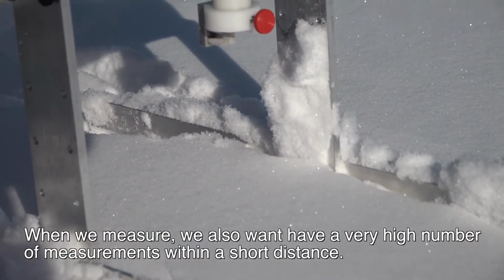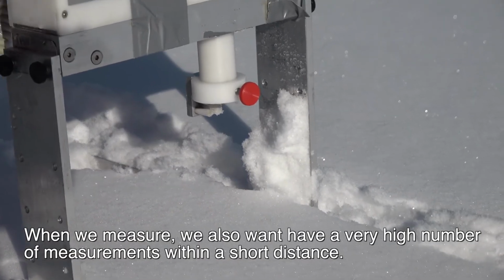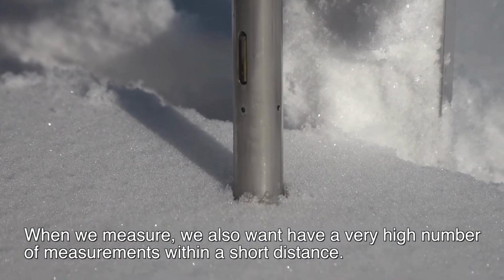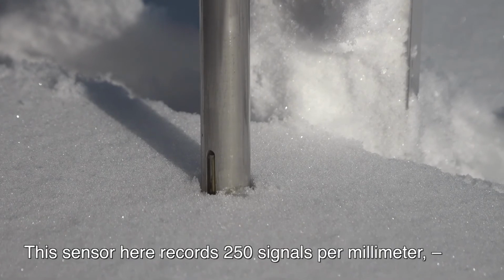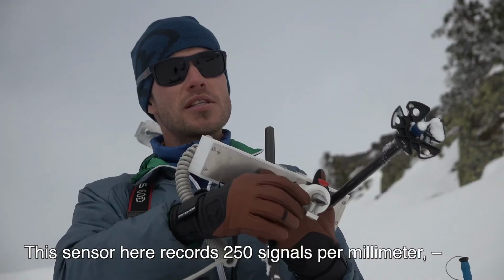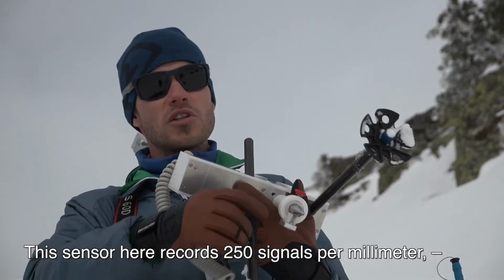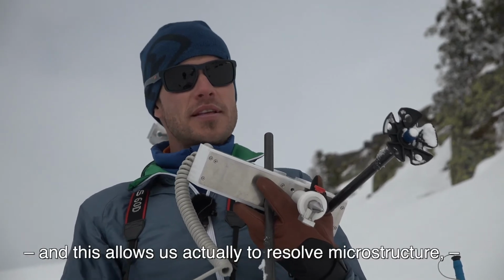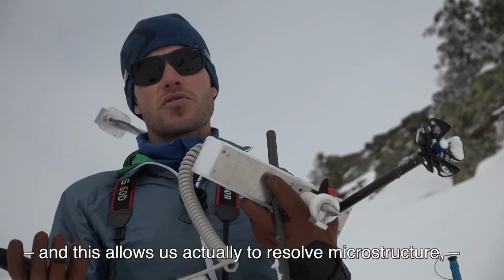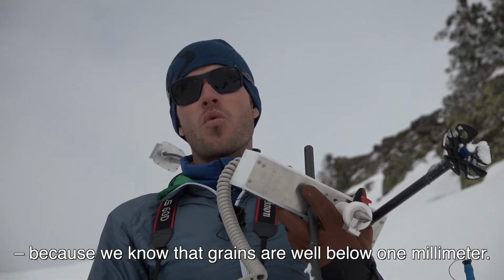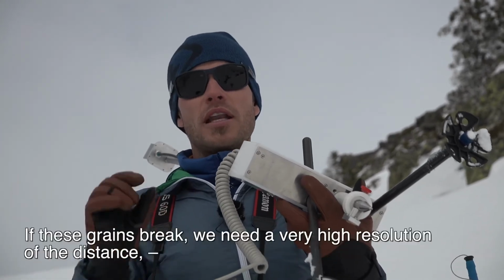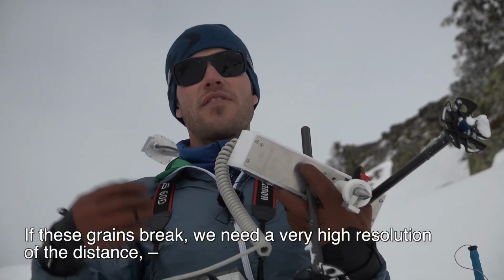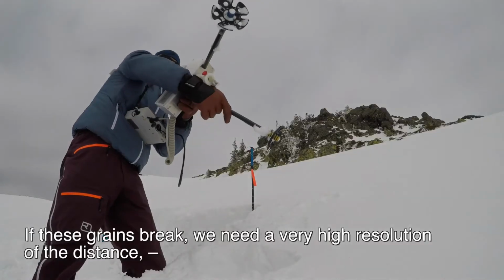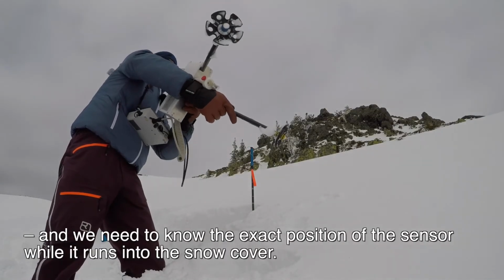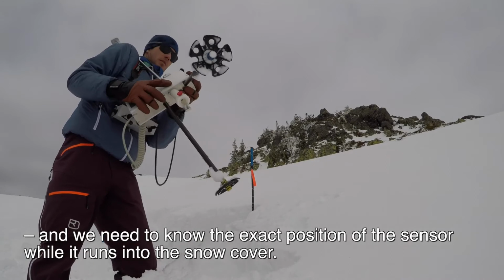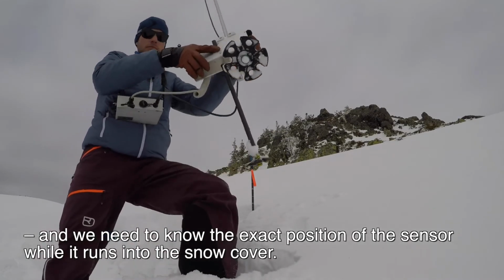When we measure, we also want to have a very high number of measurements within a short distance. And this sensor here records 250 signals per millimeter. And this allows us actually to resolve microstructure, because we know that grains are well below 1 millimeter. And if these grains break, we need a very high resolution of the distance, and we need to know the exact position of the sensor while it runs into the snow cover.